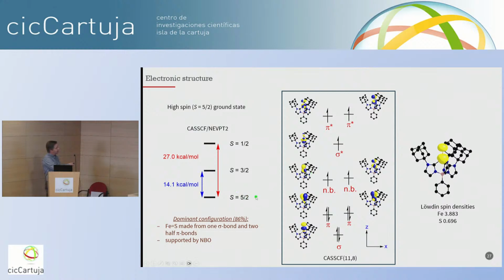We can show from CASSCF that the high spin state is the lowest energy spin state by some amount. And then this is the dominant configuration. So we have 2 electrons in non-bonding orbitals. For high spin iron(III), you have to have 5 unpaired electrons. We have 1 electron in this pseudo sigma star orbital, and then we have 1 electron each in the pi star orbitals. And so if you think about this, this means we have half a sigma bond and then 2 half pi bonds that make up this iron-sulfur double bond. And this is also supported by NBO.